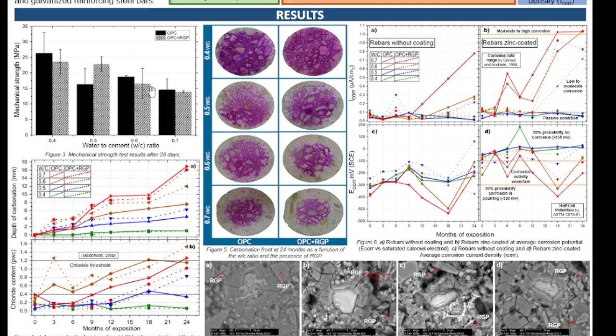Figure 3 shows the evaluation of the mechanical strength in the 4 water cement ratios 0.4, 0.5, 0.6, and 0.7 at 28 days, comparing the composition with and without partial RGP substitution. The results are not so different between the same ratio, and this can be related to the pozzolanic activity of the glass, as previous studies have shown that it is not fully active at 28 days.